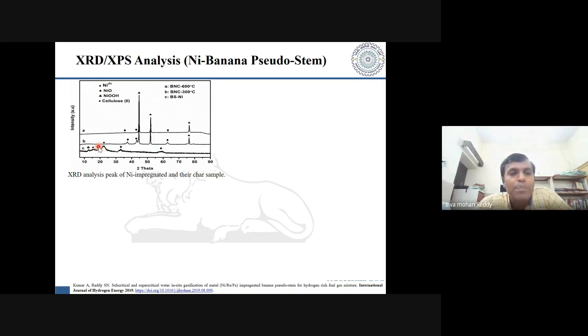Okay, so the peaks that are related to the cellulose disappear in your 300 degrees centigrade char. That means whatever cellulose was present in your actual biomass gets degraded when you subject your biomass to 300 degrees centigrade. Now you have very sharp, intense peaks related to your nickel oxide, the diamond shaped ones over here. You see one peak at 45 degree, a peak at 37 degree, a peak at around 61 degree of your nickel oxide, and you have a peak at 76 degree for your active nanometal of nickel, that is Ni, right?